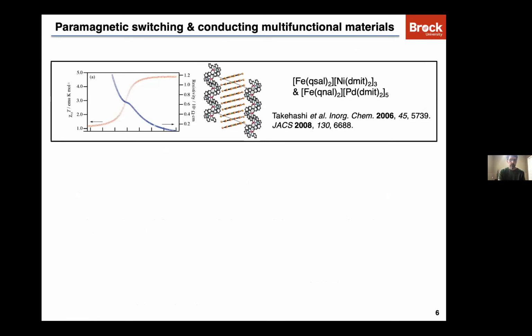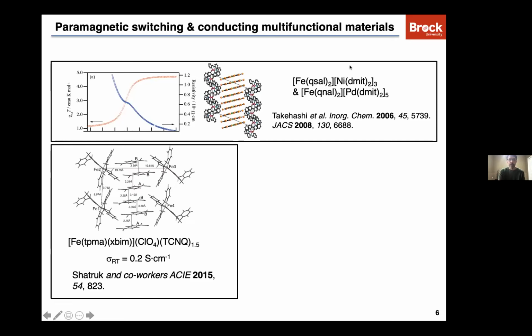So if we look at what's been published in this area, paramagnetic switching systems that also conduct, we see generally what we have are spin crossover systems. So the switching component is an iron complex that has some sort of conducting fragment, typically as an anion. So here we have nickel or palladium dmit complexes in fractional oxidation states, provides the conductivity. So you can see those are stacked in crystal structure. And then iron bis Q-sal is the spin crossover unit.